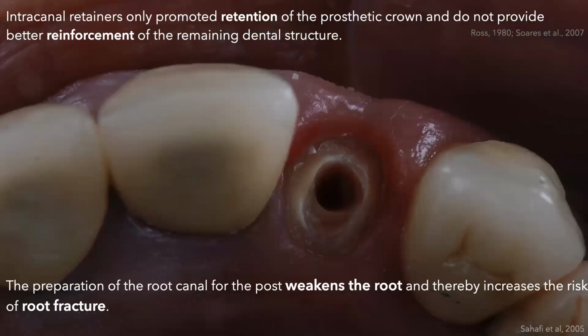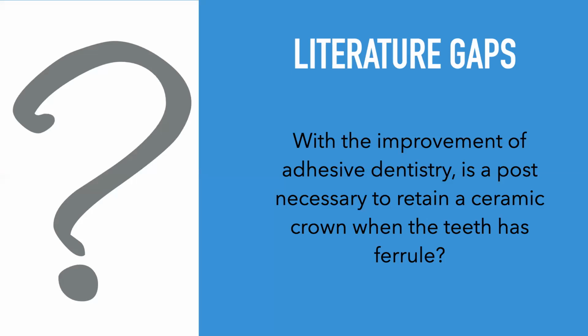So if the ferrule is so important, why are we still using posts in this kind of teeth? It's not new that intracanal retainers don't reinforce the root, but only promote retention of the restoration, associated with the fact that the preparation of the root canal for the post weakens the root. So we started to search the literature for new ways of restoring those broken down incisors with a more biomimetic approach. So our question is, with the improvement of adhesive dentistry, is a post necessary to retain a ceramic crown when the tooth has ferrule